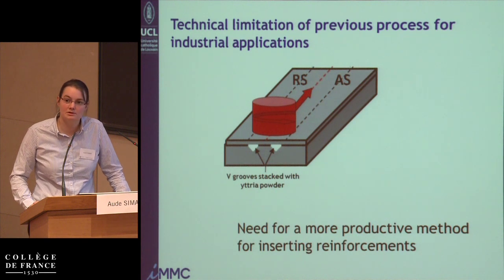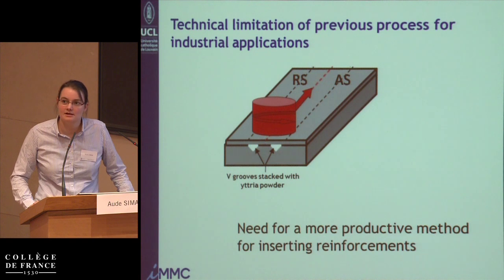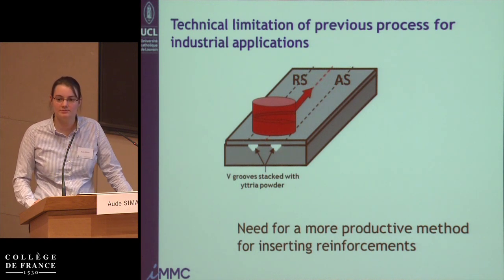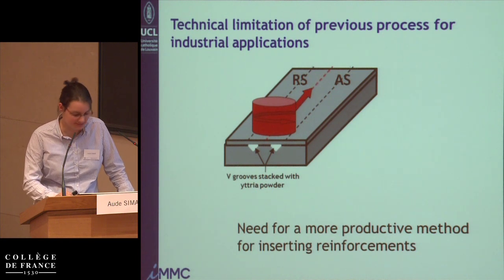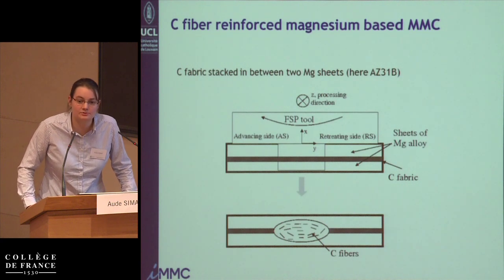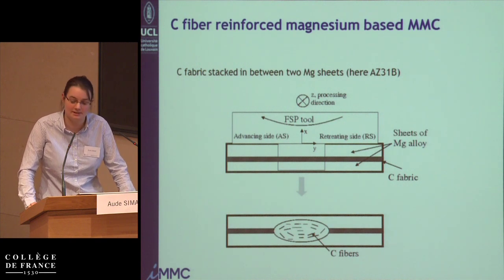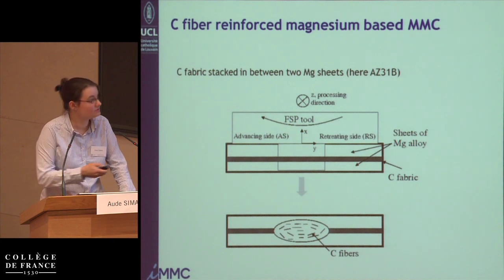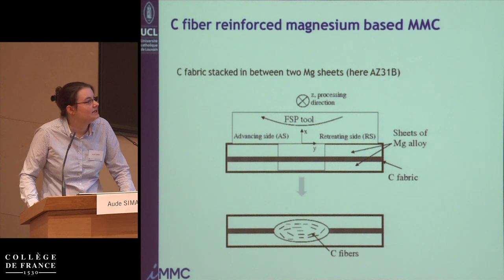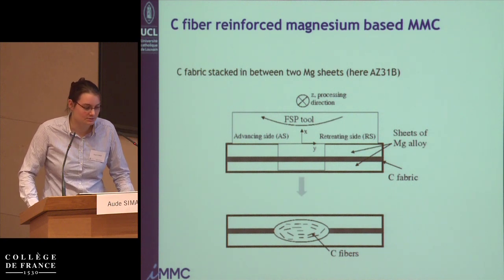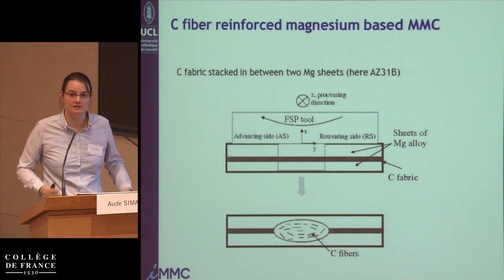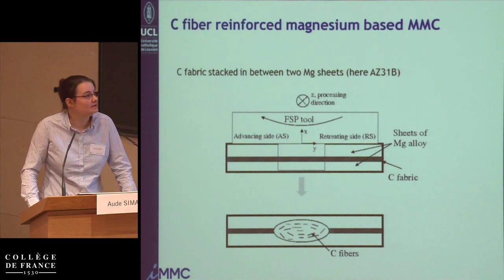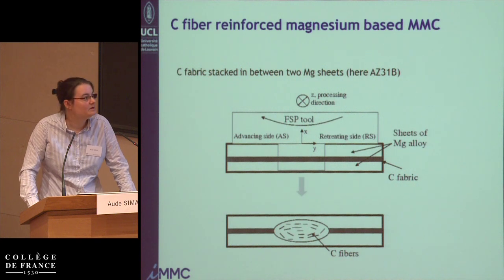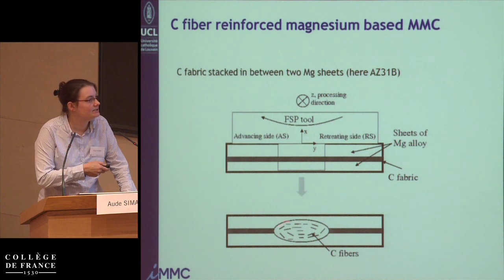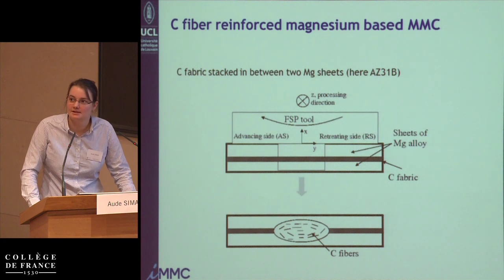So we thought, what would be a good material that we could insert easily and have something more reproducible in terms of quantity of reinforcement that we put in the material. And so this is where we came to this application, and here it's done on magnesium, but it's extendable to any kind of material. What we did is put some carbon fabric in between two magnesium sheets, the carbon fabric that is generally used for polymer-based composites. Well, these fabrics will be broken during the process, and will lead to the production of short fiber composites. So short carbon fiber magnesium composites.